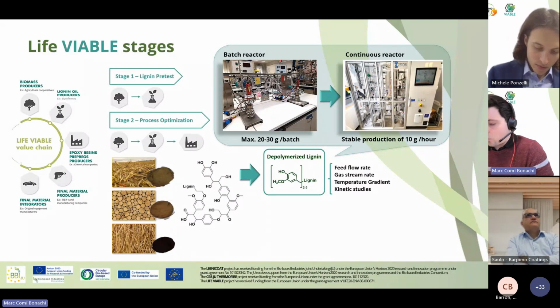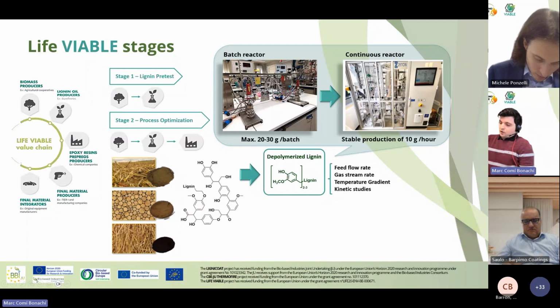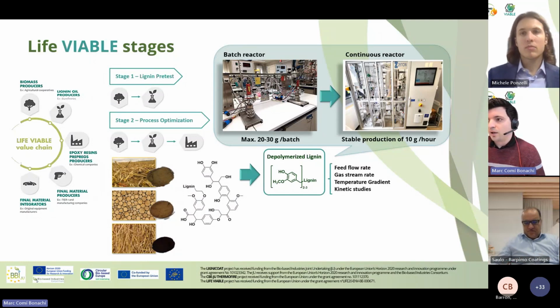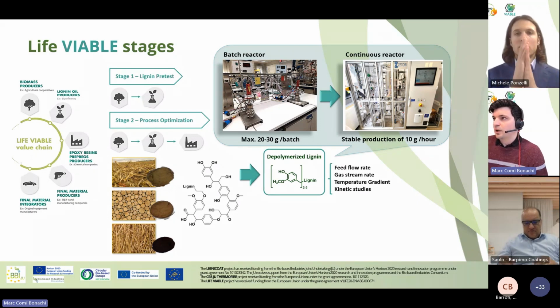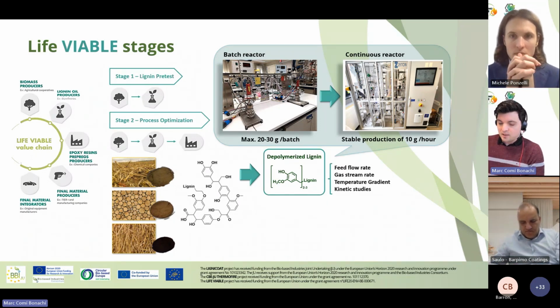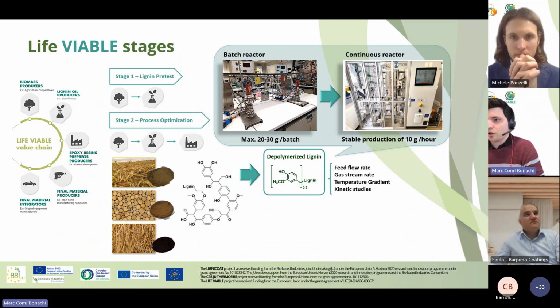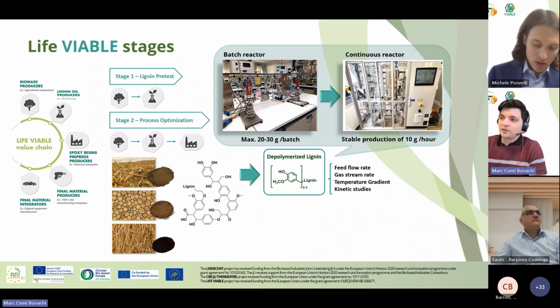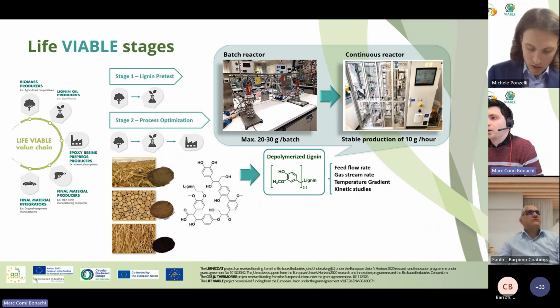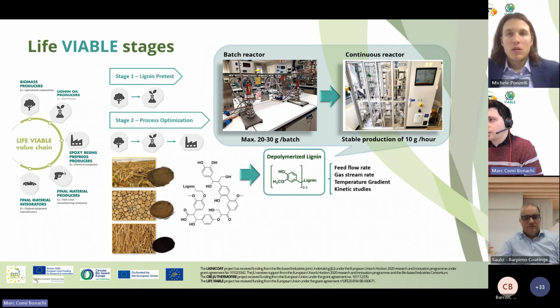But here we face a different challenge that we didn't face in the batch reactor. That is the feed flow rate, which depends on the concentration of the lignin in solvent that we are introducing in the continuous reactor, and the gas stream rate, because, as I explained, this is a hydrogenolysis reaction, so you need a constant rate of hydrogen. If you get a shortage of this gas, you don't create the phenol that you want to create, the reactive point. You are creating other modifications that don't serve the further modification, which is the glycidylation. So it's very important that the hydrogen gas rate is constant during the process.